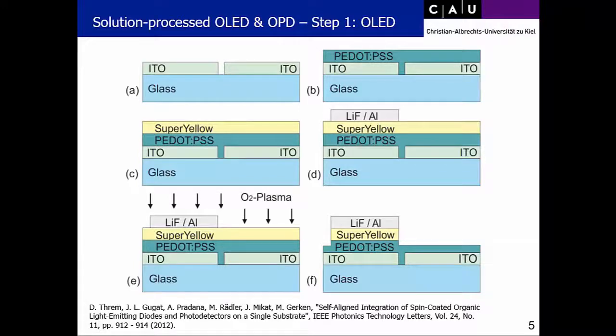For the solution processed OLED and OPD on a single substrate, and this was glass here, we used ITO as the anode, so we patterned ITO, then we spin coated this hole transport layer. The super yellow is the organic light emitting diode emission layer. We spin coated that, and as you can see with the solution processing, if you use spin coating, you have covered the whole substrate. So then we added lithium fluoride aluminum as the cathode using a mask, and used a self-masking process that this metal mask here actually protects the OLED underneath.